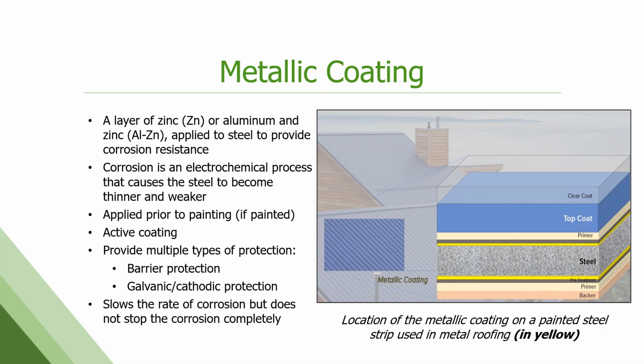Corrosion is an electrochemical process that causes the steel to oxidize, become thinner and weaker, so we want to avoid that. This metallic coating is put down prior to any painting or any additional coatings that go on. It's an active coating, and it's providing really two types of protection. You're getting a barrier protection and also a galvanic or sacrificial protection because of the zinc and aluminum both being on there. It slows the rate of corrosion dramatically, but does not stop it completely. So you will have some corrosion over time, but very little compared to other products.